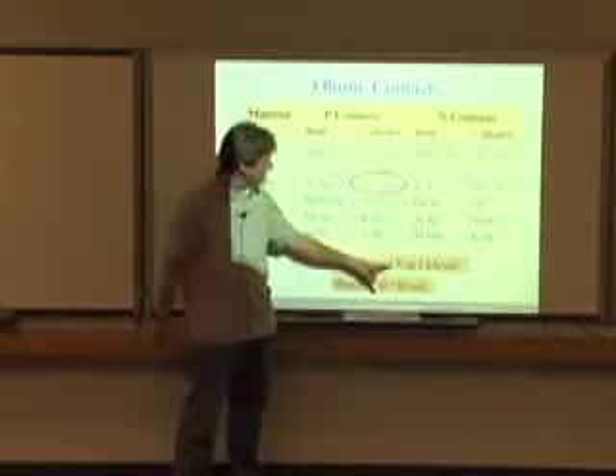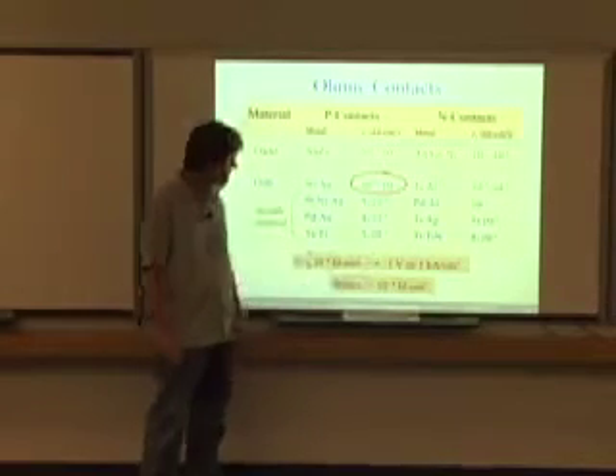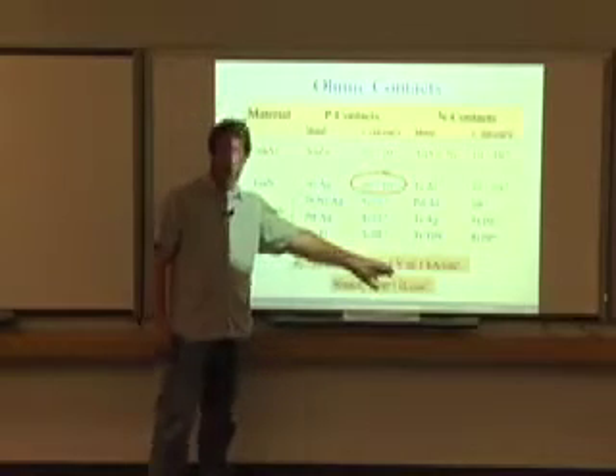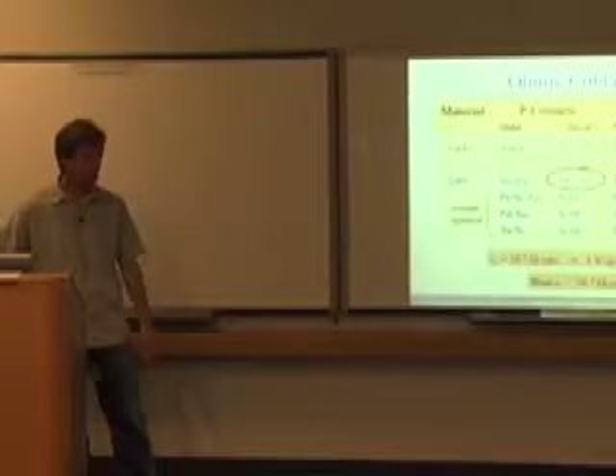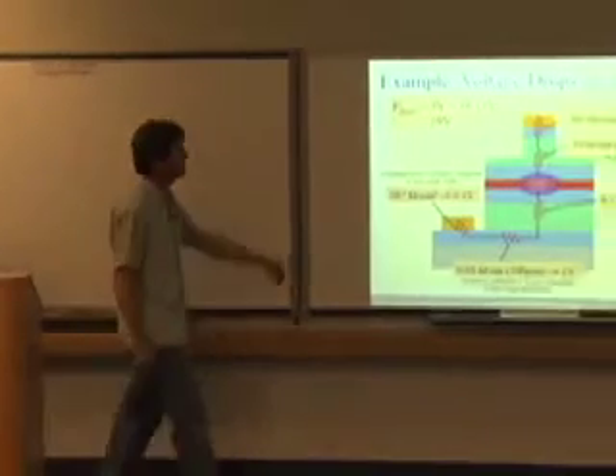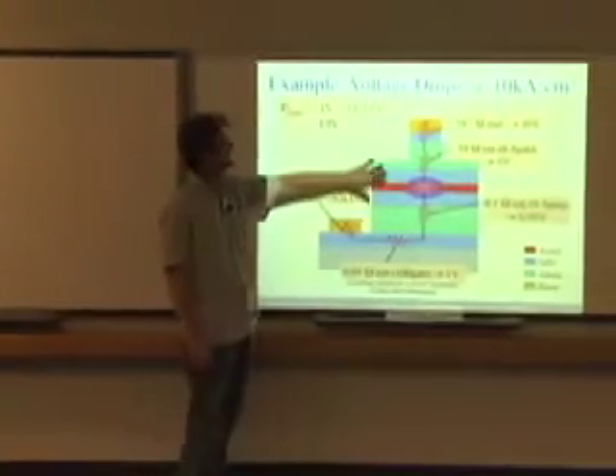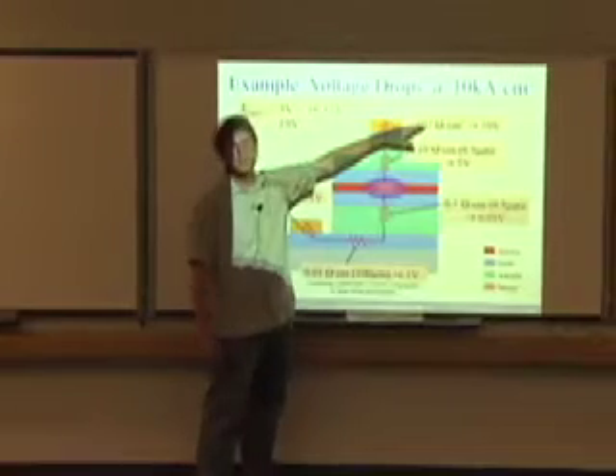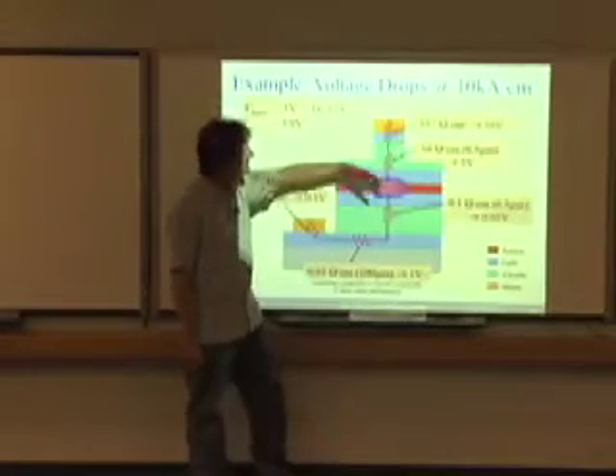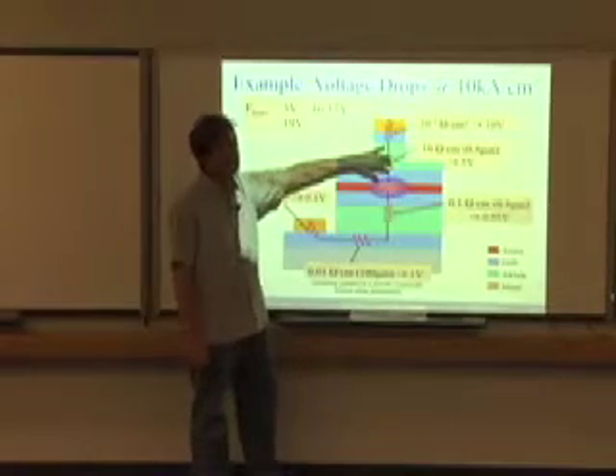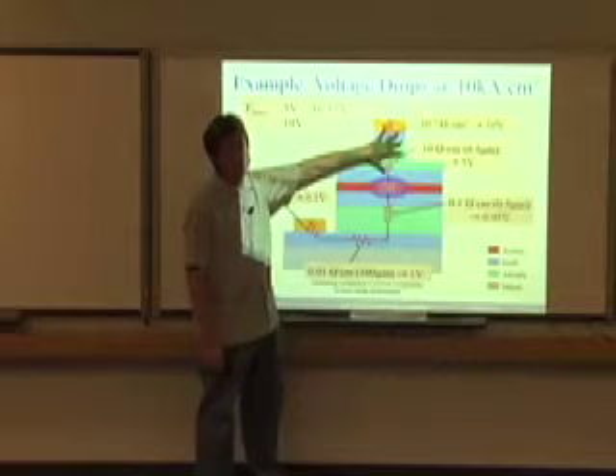So at 10 to the minus 3, this translates into, for typical laser dimensions, about a volt at 1 kiloamp per centimeter squared. Which again, you may not think that's too bad, and for LEDs, this may not be so bad. But if you're looking at a laser, which you're wanting 10 kiloamps per centimeter squared, it adds up quickly. And so if you revisit that chart I had before, you're looking at a 10 volt drop just across the P contact. Then you've got another 5 volts in this P layer up top here. So 15 volts just in your P side here.